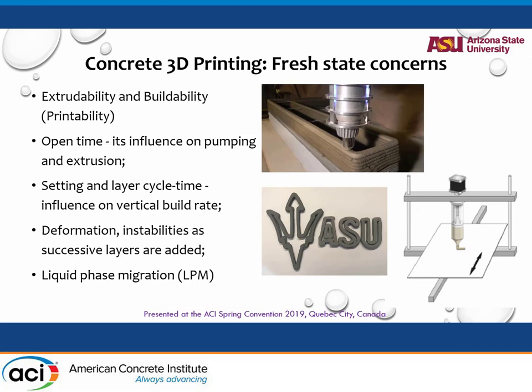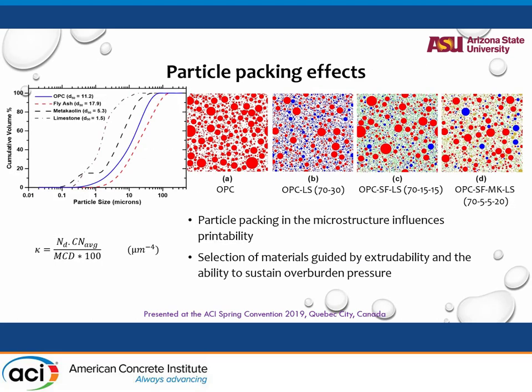For printed structures, we have a bunch of fresh state concerns — extrudability and buildability that people have talked about in detail. There is the open time, the time you can afford to have a mix being pumpable and extrudable. You have setting and layer cycle time, which influences the vertical build rate. You have deformation instabilities as layers are added, like buckling. And then there is liquid phase migration in the fresh state, which is a function of how you push your mix through the nozzle. We are trying to look at it together in a homogeneous fashion, but you quickly realize you have to break it into many manageable parts, and combining those parts is even harder than initially thought.